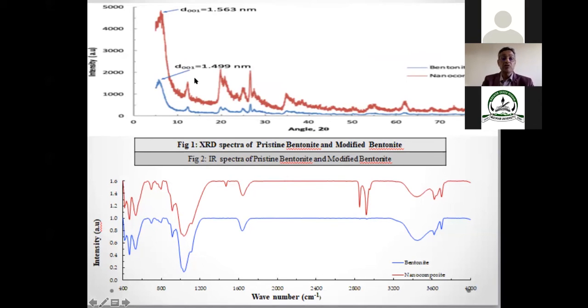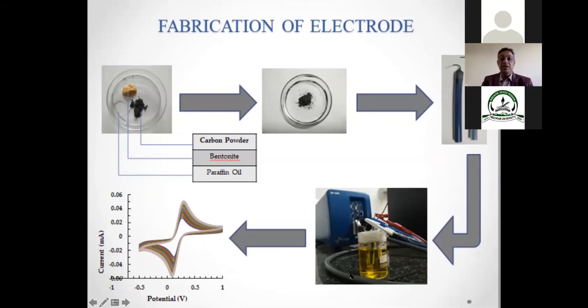The d value for the bentonite was 1.499 nanometers, which has slightly increased to 1.563 nanometers for the modified material, according to this XRD data. And this is the fabrication of the electrode that we have done with the help of the material.